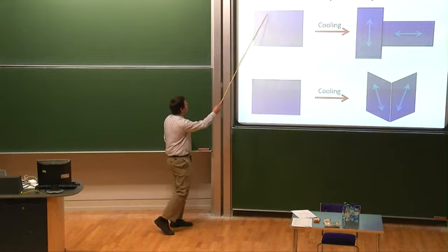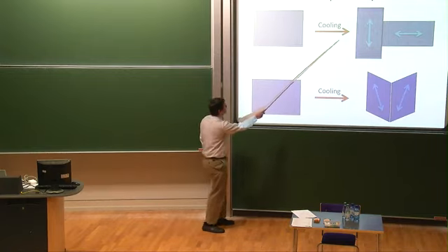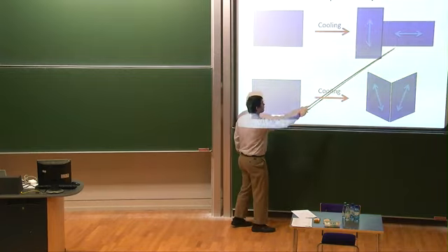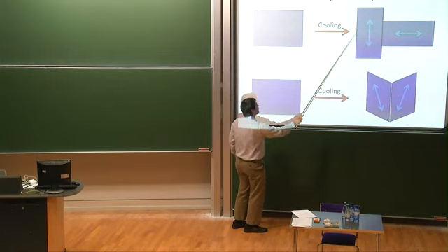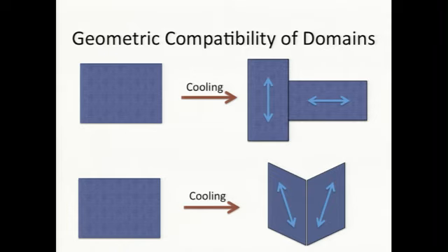So here we imagine something in the isotropic state. If I cool it, and it tries to make a domain structure that looks like this. Okay, so one oriented like this and correspondingly stretched in this direction, and then one oriented horizontally and correspondingly stretched in the horizontal direction. Okay, that's very bad, because although individually these domains are completely happy, they've stretched along their director by the right amount, this boundary has ripped, or at the very least become extremely stressed, and that's not good. There's definitely going to be a very strong energy penalty associated with that.